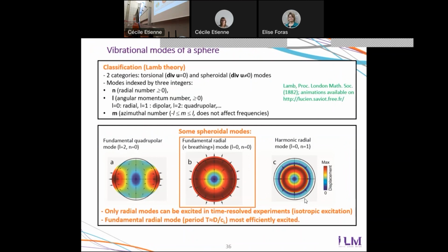So I will summarize to make it short. For spheres, the theory of the vibrational modes was done by Horace Lamb at the end of the 19th century. Not for nanoparticles, just for vibrations of spheres in general. He found that modes can be classified in many different categories, so it looks a bit complex. However, for time-resolved experiments on nanoparticles, the vast majority of these modes cannot be excited. Only simple modes called radial modes, which have an isotropic displacement, can be excited. So it's only a tiny category. And among these, the fundamental one, which is called the breathing mode, which does not have a displacement node, is excited more efficiently. So it's only this mode that is detected in time-resolved experiments on nanospheres.